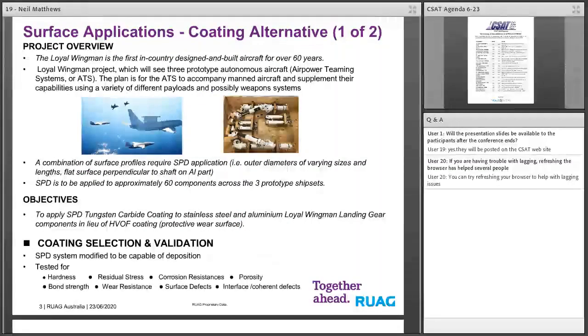Okay, so we've had some significant achievement in the coating area. What has happened in Australia, it's the first time in over 60 years we've actually built an aircraft. It's a very large drone. It's being produced by Boeing. The Australian government has ordered 3 of these in the initial order. And as you can see from the picture, it's supposed to operate with some of our aircraft, the AWACS and even the F-35. RUAG has a contract to build the undercarriages. And as part of that, we offered up SPD as an alternate to existing coatings and also in replacement for HVOF. So we'll be applying this to about 60 components across 3 prototype ship sets.